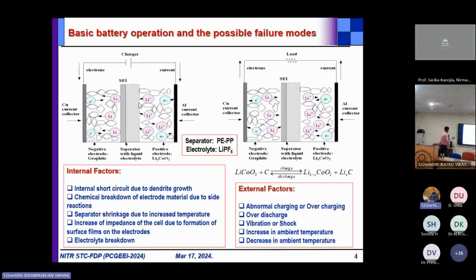Because of that, the overall internal impedance of the battery cell will increase. Now, a battery is a charge storing device, so typically it can be realized by RC networks if you consider electrical equivalent models. The capacitive nature is there because it is storing the charge at the interfacing layer of the cathode and the electrolyte, as well as the anode and the electrolyte, very much like a capacitor, where we have two plates with a dielectric in between. Because of this SEI layer formation, the overall impedance of the battery will gradually rise, and that is a sign of degradation. The number of lithium ions which can participate in charge storing within the cell will gradually reduce due to the obstruction it faces from the deposition of the SEI layer.